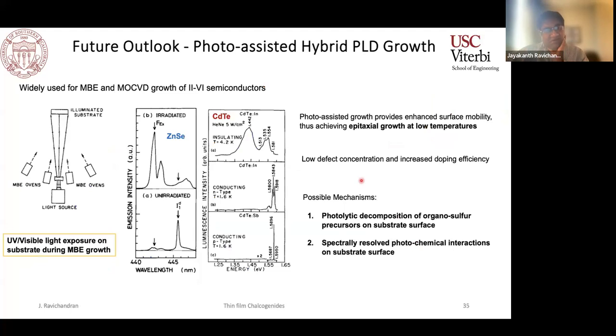So one of the things that we are starting to think about is using some photo-assisted techniques to control the surface mobility and also even precursor decomposition. There's a ton of work in the II-VI and also III-V systems where people have used these approaches in the past. It might benefit us a lot more, given that the vapor pressure mismatch between transition metal and chalcogen is way more dramatic compared to even the main group ones that I show here. And they did see in many of these cases significant improvement in the structural, optical, and optoelectronic quality of the films that they were growing.